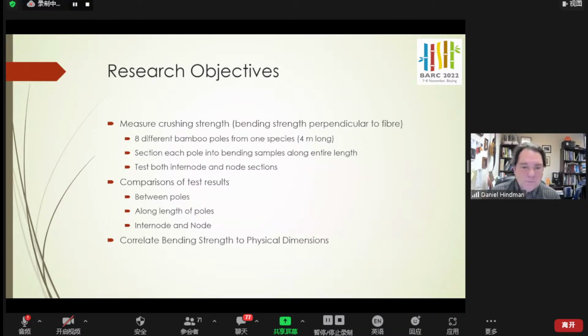So unfortunately, one of the disadvantages of my research is that we do not have an exact position of where each pole is located within the overall culm of the bamboo pole. So each of the poles is 4 meters long, and essentially we sectioned each of those 4 meter long pieces into about 50 centimeter lengths that we then tested for the bending strength perpendicular to fiber. We tested both internode and node sections.